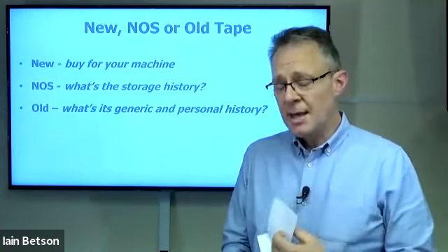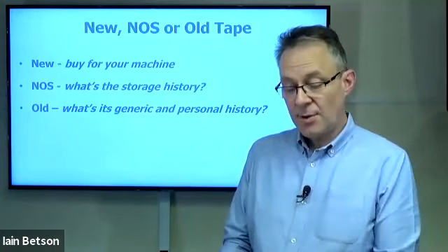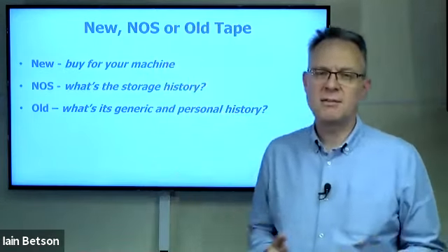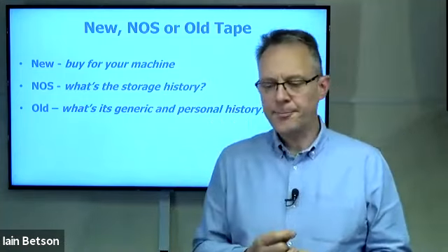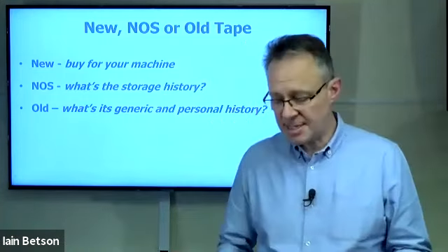Looking at the details of the tape, they do go into it on this website about all the different history of it, and indeed some of it was acetate tape, acetate backing. The base itself is invariably polyester. 90% of tapes, and let's call them modern tapes, anything from the 1970s onwards, were polyester. But ones prior to that could have been acetate, and they have a history of going very brittle, and literally the tape would just snap in half, almost like tearing some tissue. Really, the machine would just split it. It hasn't lasted that well. Same as the good old cassette tapes.